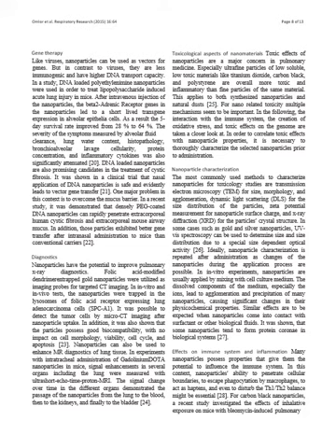Nanoparticle characterization. The most commonly used methods to characterize nanoparticles for toxicology studies are transmission electron microscopy for size, morphology, and agglomeration, dynamic light scattering for the size distribution of the particles, zeta potential measurement for nanoparticle surface charge, and X-ray diffraction for the particles' crystal structure.